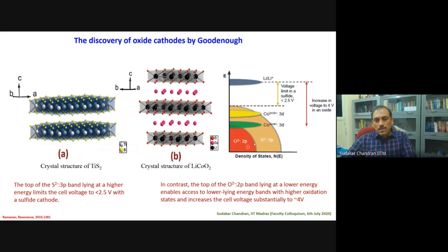So he realized that using oxides, because the oxygen 2p bands lie at lower energy, enables access to lower lying energy bands, and therefore one can achieve increased voltage output. He realized that aspect, and then he explored structurally similar compounds, LiMO2. Titanium disulfide has a close packing structure of sulfur, and the titanium sits in the octahedral sites. They form a van der Waals layer compound, and in between these layers, lithium goes in and out. So he found a similar compound in LiMO2.